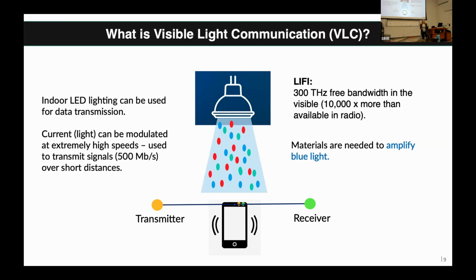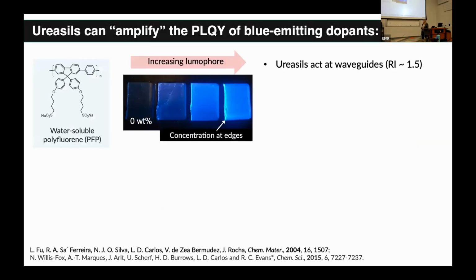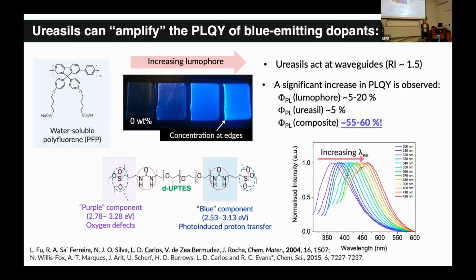So for VLC, one of the challenges is the spectrum of the light source. And actually, we need materials that are going to amplify the blue light component. We had previously shown that ureasils can amplify the photoluminescence quantum yield of blue-emitting dopants. So we put this blue-emitting polyfluorene into our ureasils, and we saw two interesting features. The first thing we saw is the emission was concentrating at the edges of our materials. This is because the ureasils themselves act as waveguides. This will be important for later applications. The other interesting feature was as we increased the lumophore concentration, we saw a really significant increase in the photoluminescence quantum yield.